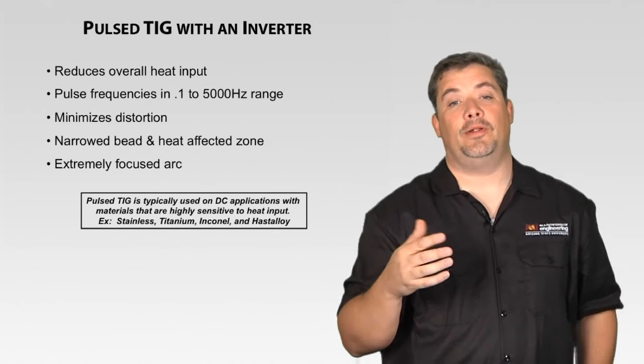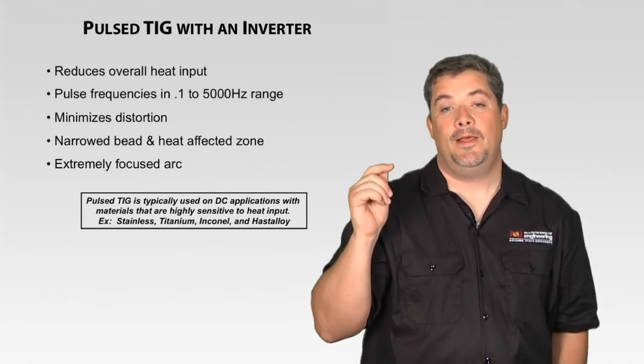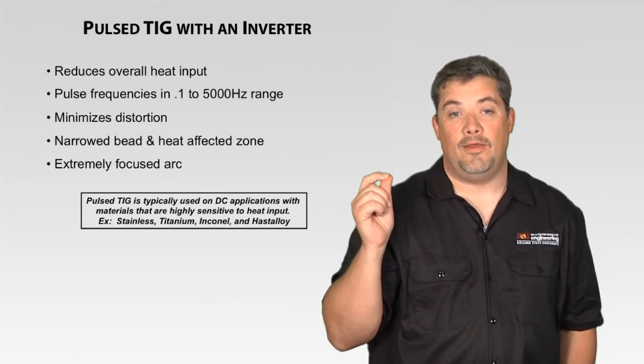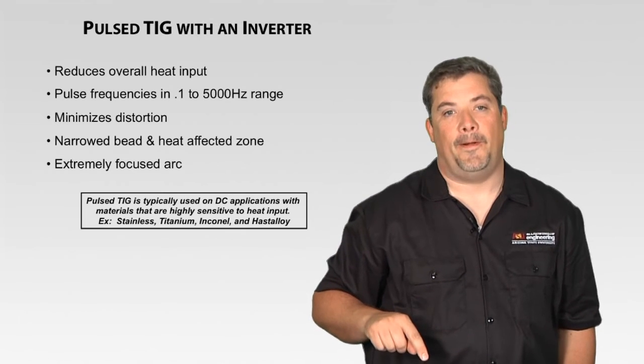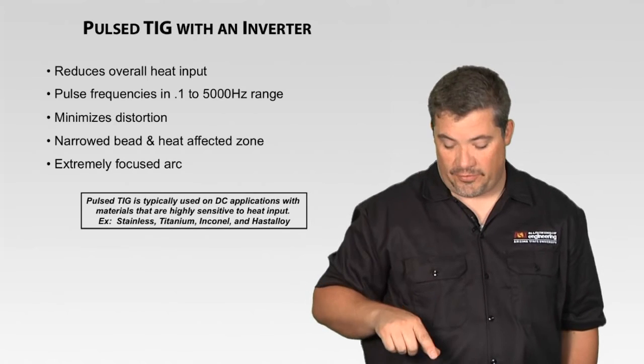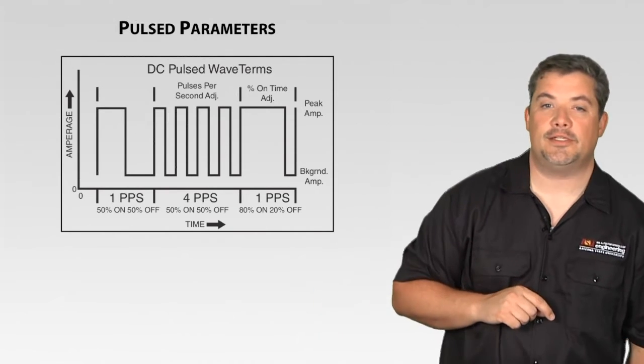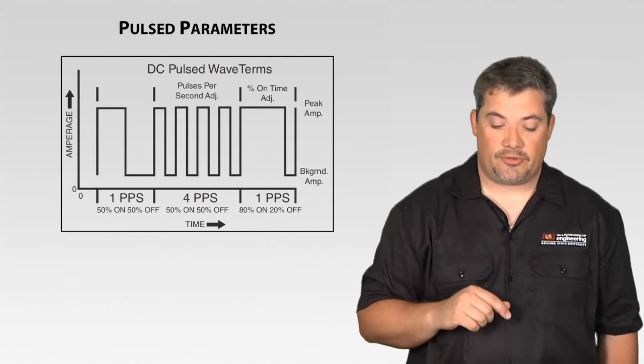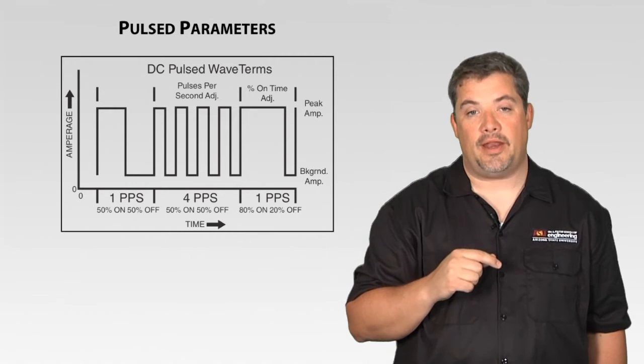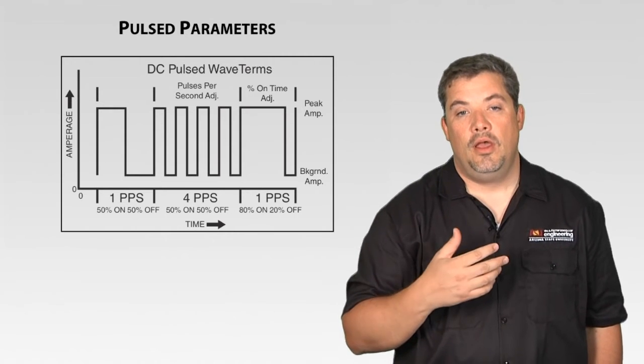So pulse welding can be pretty nice. You get a narrower bead, you get a narrower heat affected zone, you have a much more focused arc, and again, you get rid of that surface tension off of things like Inconels and Hastelloys. So it's just an illustration showing some of the things we look at in pulse welding.